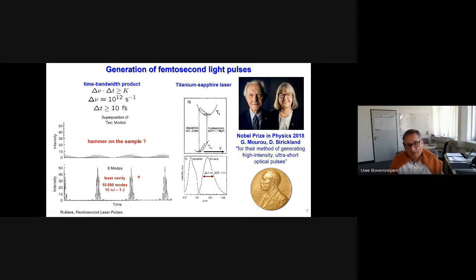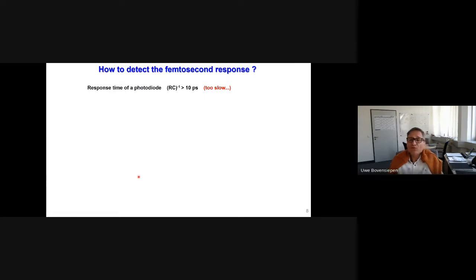Now, let me make a comment. These are very intense pulses, and we bring them to our sometimes delicate samples, so we have to worry whether these samples are stable, and in a way we hammer on the sample. I will come back to this point. Now, how do we detect the femtosecond response? If you simply take a photodiode, you all know that there is an ohmic resistance and a capacity in this diode, and the respective time scale is typically longer than 10 picoseconds. So we cannot use this for ultra-fast spectroscopy.